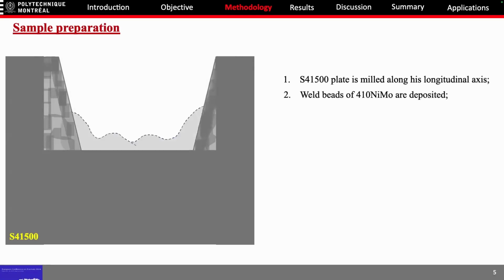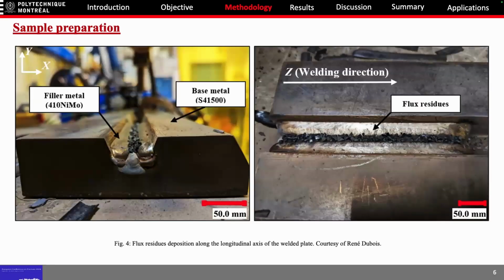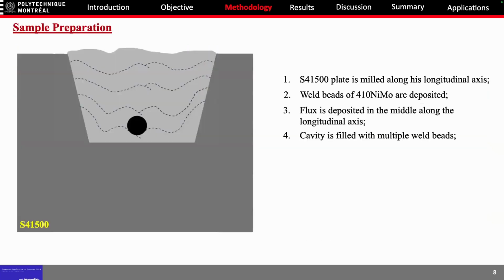Then weld beads of 410 nickel molybdenum are deposited at the bottom of the cavity, and the flux residues are deposited all along the longitudinal axis. This is a real-time picture of the process. As you can see, the flux residues are deposited all along the longitudinal axis, and then covered by weld beads. Then the cavity is filled up with multiple weld beads, and the excess is gouged.